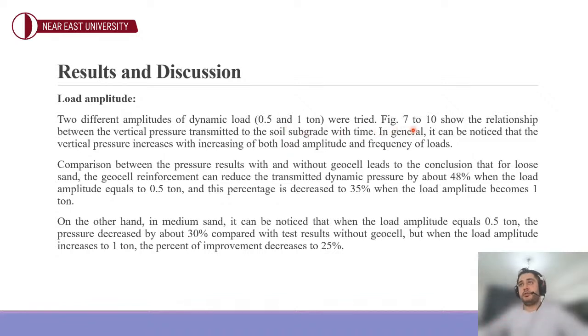Figures 7 to 10 show the relationship between the vertical pressure transmitted to the soil with time. For comparison's sake, if we are using loose soil, 30% relative density and 0.5 ton amplitude, the reduction of the transmitted pressure reached 48% if we use geocell reinforcement, and this value decreases to 35% if we are using 1 ton.